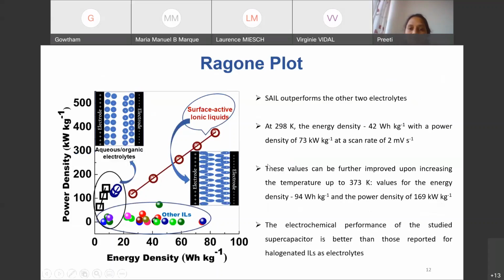The Ragone plot gives us energy density versus power density, and it shows how this surface active ionic liquid is important and outperforms the other two electrolytes, as compared to other reported ionic liquids. These black circles, black squares and blue circles show aqueous and organic electrolytes, which lie in the low power density and low energy density region. Other ionic liquids have a higher energy density but very low power density.